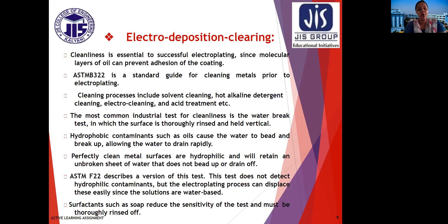The most common industrial test for cleanliness is the water break test, in which the surface is thoroughly rinsed and held vertical. Hydrophobic contaminants such as oils cause the water to bead and break up, allowing the water to drain rapidly. Perfectly clean metal surfaces are hydrophilic and will retain an unbroken sheet of water that does not bead up or drain off. ASTM F22 describes a version of this test. Surfactants such as soap reduce the sensitivity of the test and must be thoroughly rinsed off.